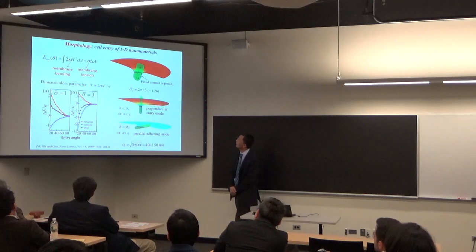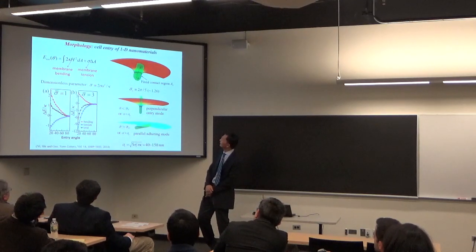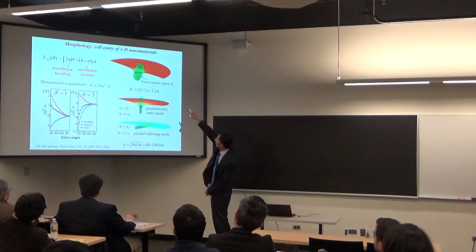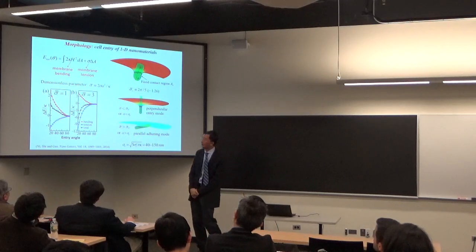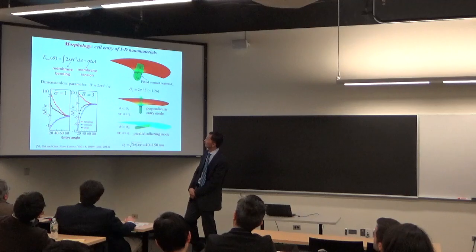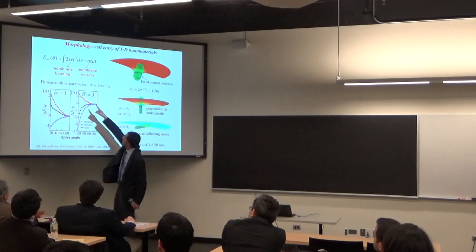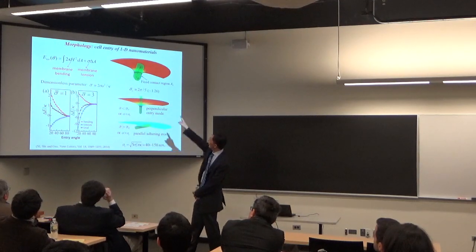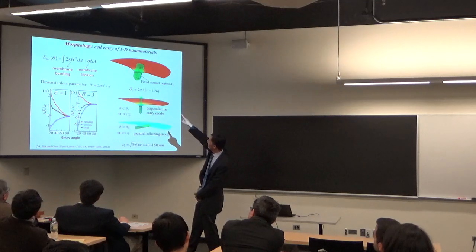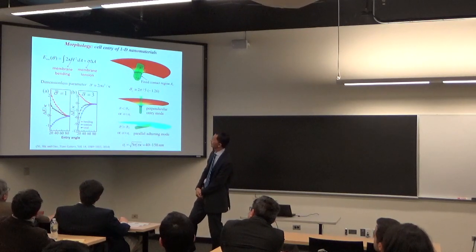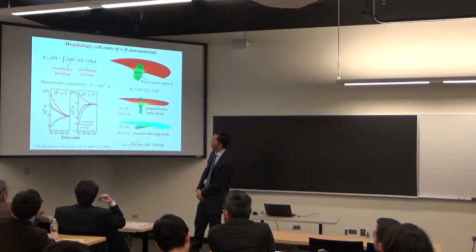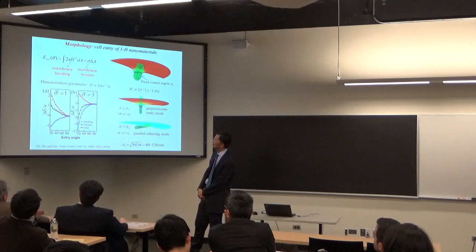So first example, I want you to imagine I have a carbon nanotube or some nanofiber in the process of entering a cell, as that picture shows. So I can write down the free energy of the system. We always deal with the energy. There are 2 terms. The first term is the membrane bending energy, because for that nanomaterial to go into the cell, the membrane has to wrap around the particle and form a curved surface. That causes bending elastic energy. So kappa is the bending rigidity, H is the mean curvature of the cell surface, integrated over the area.